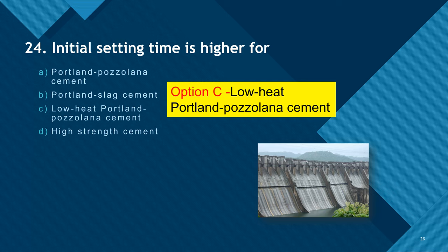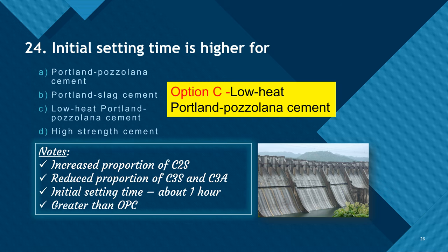In the term low heat, we can infer that the cement contains very low amounts of C3A. C3A is tricalcium aluminate, which is responsible for a high rate of hydration, and consequently has a lower initial setting time. So by lowering the amount of C3A as a Bogue compound in a cement, we can produce low heat PPC, and that will be used to construct large massive dams and structures like these. So we have a reduced proportion of C3S and C3A, and consequently an increased proportion of dicalcium silicate. So initial setting time has to be about 1 hour. It is much greater than OPC. For OPC it is more than 30 minutes. For low heat PPC it is about 1 hour.